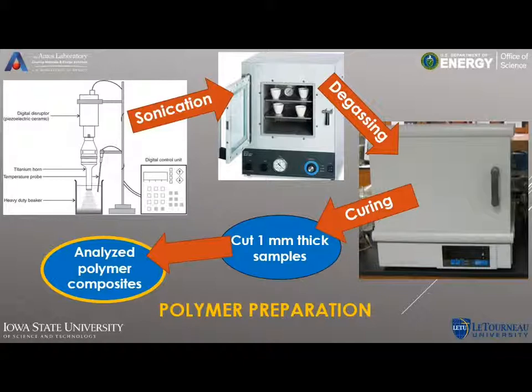After they were polymerized, we took the samples out, removed them from the rubber molds, and then cut them into thin 1 millimeter thick strips. These we could then analyze by the different instrumentation.